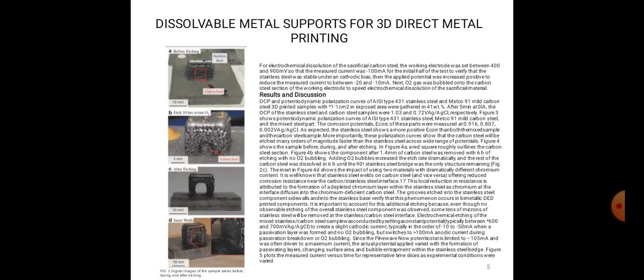Now dissolvable metal support for 3D direct metal printing. For electrochemical dissolution of sacrificial carbon steel, the working electrode was set between 400 and 900 millivolt, so that the measured current was 100 milliampere, and the initial half of the test verified that the stainless steel was stable under the cathodic bias. Then the applied potential was increased positively to reduce the measured current to between -20 and -10 milliampere, meaning we have current in the negative direction. Next, O2 gas was bubbled onto the carbon steel section and work electrode to speed up electrochemical dissolution of the sacrificial metal. After this process we can achieve some optimization of post-processing in 3D printing of metal samples.